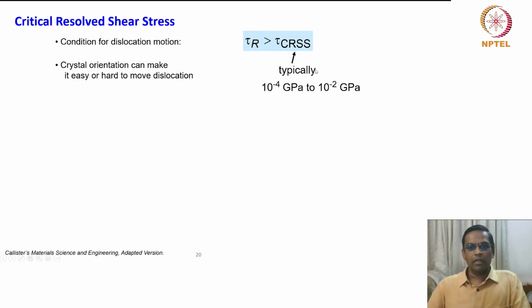The critical resolved shear stress values are typically of 10 to the power minus 4 GPa to 10 to the power minus 2 GPa. The crystal orientation can make it easy or hard to move a dislocation. Okay, this is very important. We will look at the details as we move along.